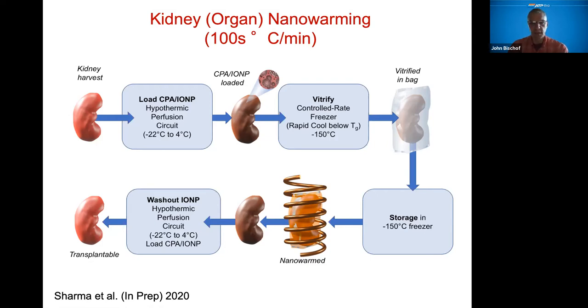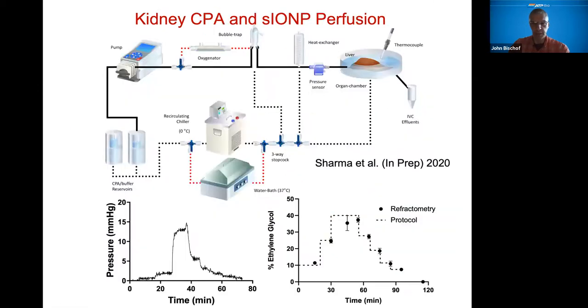But the concept is really that we're going to try and put the cryoprotective agent in, and we're going to try to put the nanoparticles in, vitrify, and then put it into the radiofrequency coil to rewarm in a fast and uniform way when we need the organ, and then wash out the iron oxide nanoparticles and the cryoprotective agents, and then use the kidney. So this is the concept, and I'll show you sort of where we are with our data.